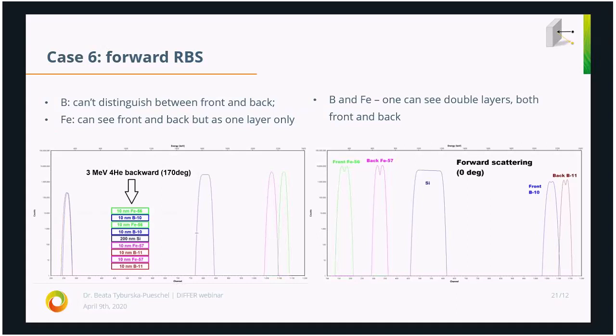Here, this we really use in reality. I cannot show you the exact case because this was done for ASML, so I constructed an artificial sample. I constructed a membrane where we have layers of iron and boron, so iron, boron, iron, boron. Then in the middle we have some silicon, and then again we have iron, boron, iron, boron. On purpose, I used different isotopes of iron and boron, so we can clearly see which are the top layers and which are the bottom layers.